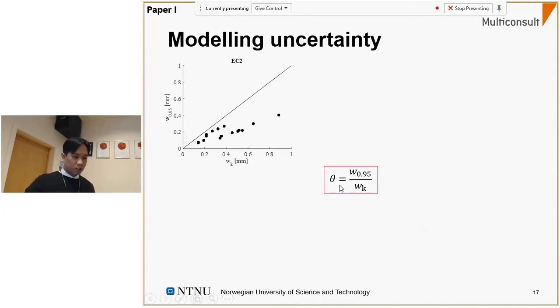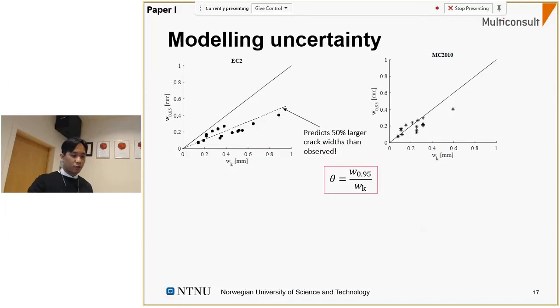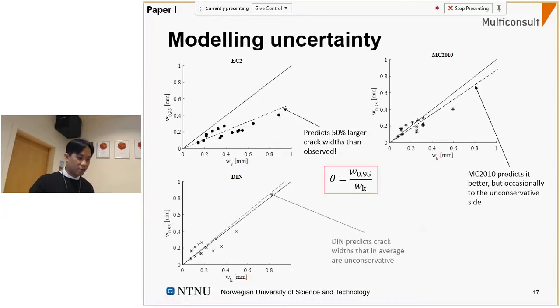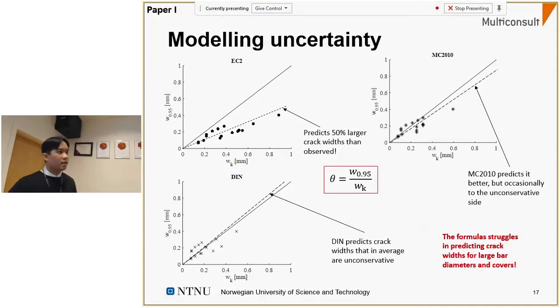Now, if this fraction here is equal to 1, then all of these dots would have been aligned along this straight line. However, as we see here, Eurocode 2 predicts crack widths that on average are 50% larger than the maximum crack widths observed in the experiments, meaning that the Eurocode 2 is overly conservative. The Model Code 2010 predicts the crack widths better, however, occasionally to the unconservative side here, which are the dots that are marked on the upper side of this straight black line. The German Annex predicts crack widths that on average are unconservative, which is not convincing. The main message and the main conclusion here, however, is that the formulas struggle in predicting crack widths for large bar diameters and large covers.